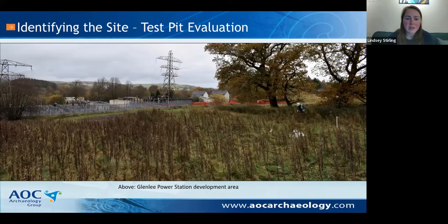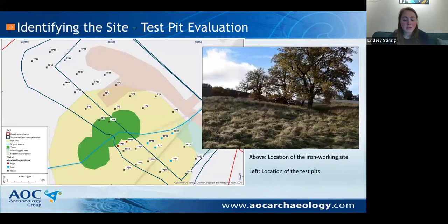So it's just a map of our grid of test pits there. We had 37 test pits across the new substation footprint, and they were located on both sides of the stream. But what we quickly discovered was that those on the north side of the stream really didn't have any metalworking material at all coming out of any of them.